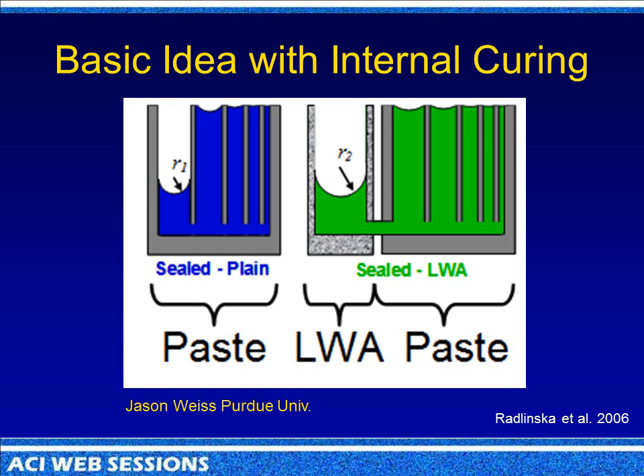Well, it pulls the absorbed water out of these larger pores, sucks it into the cement paste, and therefore you always have 100% moisture needed for the hydration of the cement.